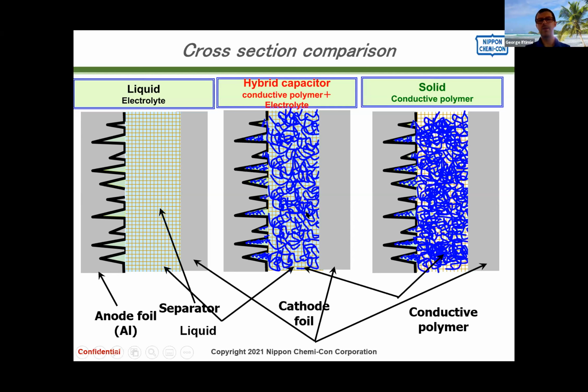The hybrid capacitor is really what it is. It is a hybrid between a polymer and a liquid. So it starts life as a conductive polymer, and then it has a secondary impregnation where we add the electrolyte. And the liquid electrolyte's main purpose is to protect the polymer material. The polymer material is very sensitive to humidity, and that makes humidity applications, like outdoor applications or automotive applications, problematic for full polymer capacitors. And this sensitivity and the drawbacks and the side effects of that increase almost exponentially as the voltage rating of the part increases.